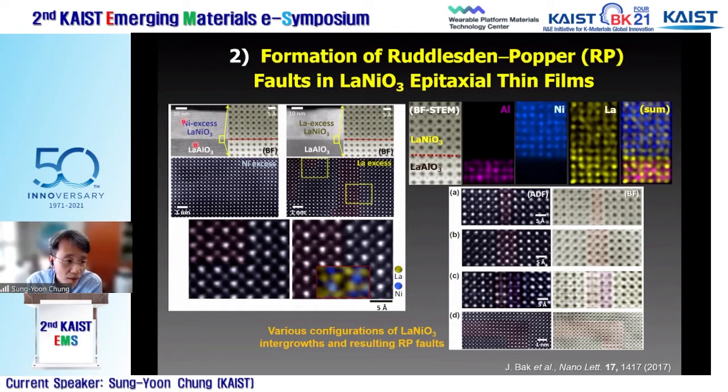One is the nickel excess, which has a perfect clean crystal structure, a perfect perovskite structure. But when we add some La excess, in the 1 or 2% La excess sample, as you can see in this image, many Ruddlesden-Popper two-dimensional defects can be observed.